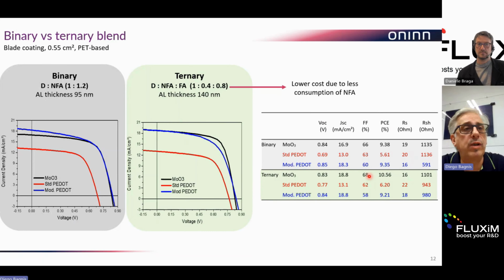So just to give a brief overview of what I mean when we're speaking about binary and ternary. In the binary case, you have the non-fullerene acceptor and the donor. And as I mentioned before, with the standard molybdenum oxide, you are able to achieve pretty interesting results, close to 10%. Just to remember that we're speaking about a green solvent, working in air, on a flexible substrate. And so in that way, you are already reducing the performance, so this close to 10% is a pretty nice result under the conditions I mentioned.